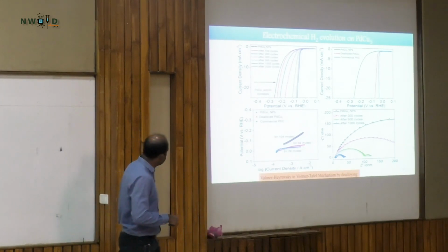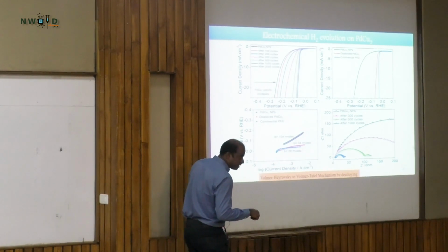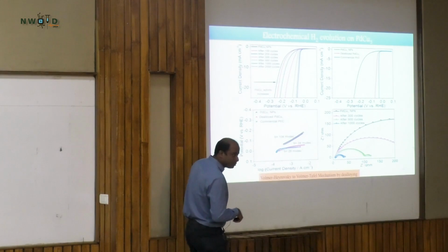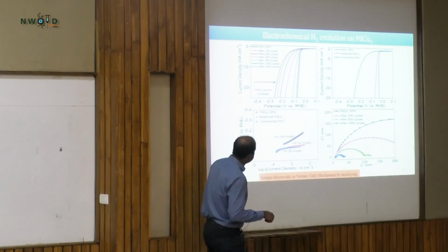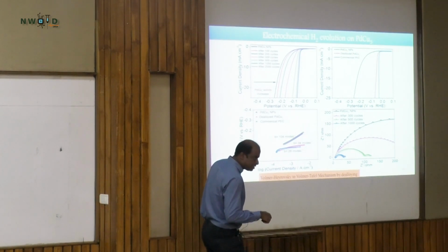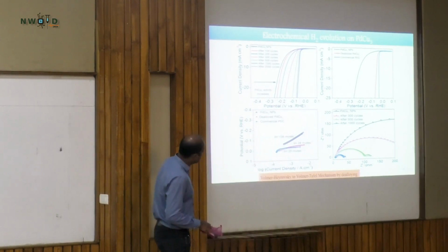So there's the famous Tafel law. It's nothing but the B value, we are getting 34 for our catalyst, and platinum is 29. It's close to platinum. And exactly, this is another charge transfer kinetics, and you can see that, this Nyquist circle, whichever is the lowest means less charge transfer, and that gives the better activity in our case.